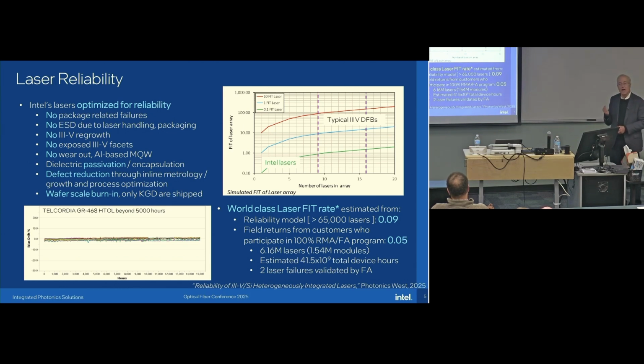Part of the reason it's more reliable is that there's no exposed III-V facets. Everyone making indium phosphide lasers or gallium arsenide lasers, facet damage has often been the issue. But now everything is buried underneath SiO2. So none of these transceivers are hermetic, whereas most indium phosphide packages have always been hermetic. Nothing's hermetic here, but the reliability is much better.